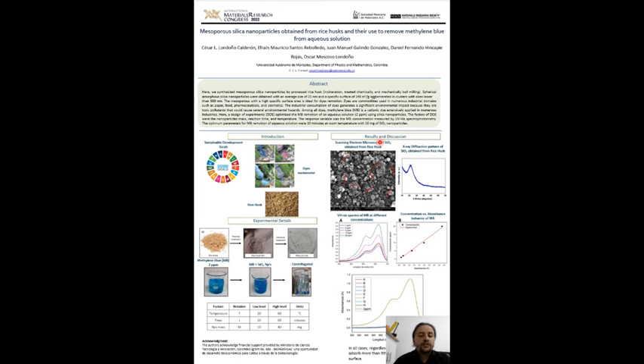From X-ray fluorescence, it was determined that effectively up to 98% of the sample finally obtained after thermal treatment and leaching corresponds to silica. Most nanoparticles have a spherical shape with a diameter between 14 and 28 nanometers, which form agglomerates with size ranging between 123 and 557 nanometers. The nanoparticles obtained under this condition have a specific surface area of 148 square meters per gram according to BET results.